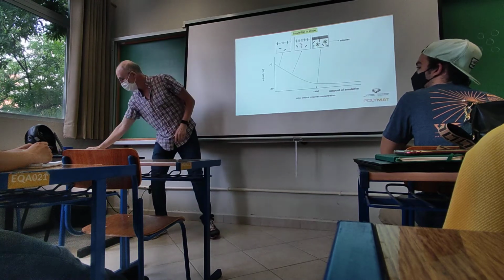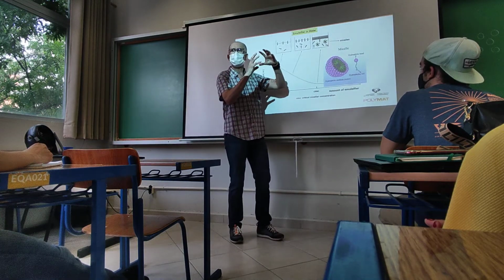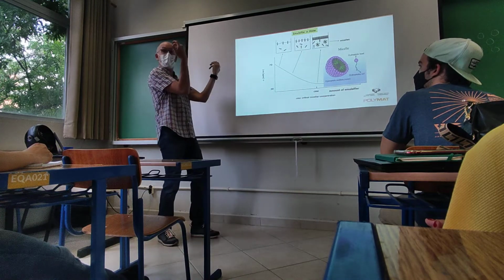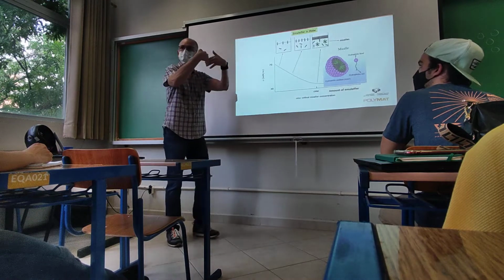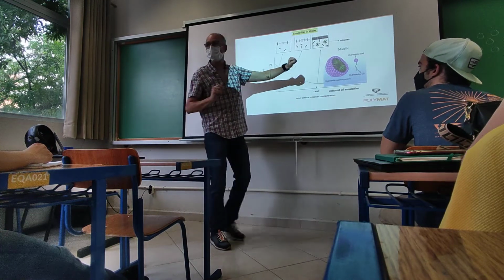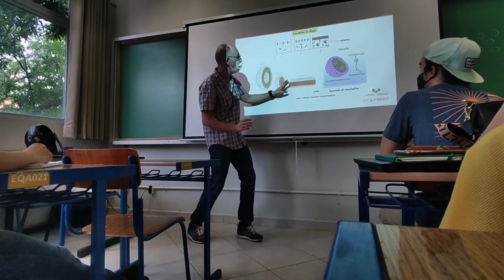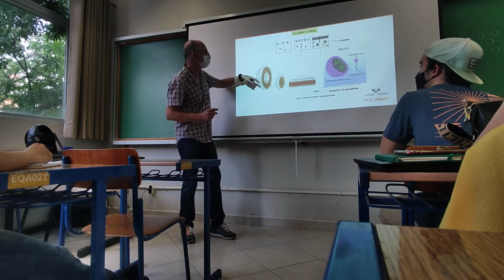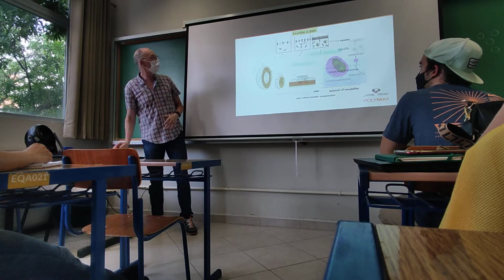So the surfactants aggregate, forming structures like this, spherical micelles, where the hydrophilic part will be towards the exterior, in contact with the water, and the hydrophobic will be towards the inside. And it can contain hydrophobic material inside. Sometimes, depending on the structure of the surfactants, you can produce also bilayers or vesicles or liposomes. Right? So there are different structures that can be produced.